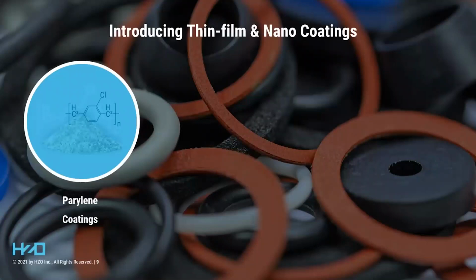Coating is dense and uniform. It's a long chain polymer. It's completely conformal on the substrate. The molecules can penetrate into micron-sized gaps, so we can get under BGAs and coat the solder balls and surrounding leads without leaving any voids.